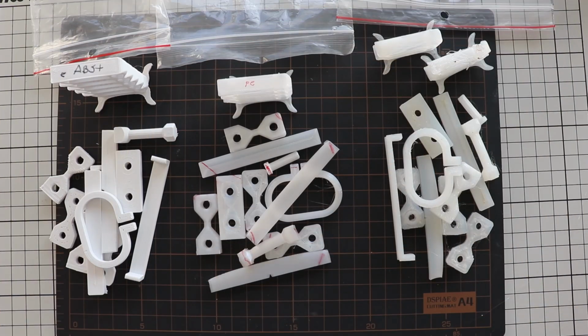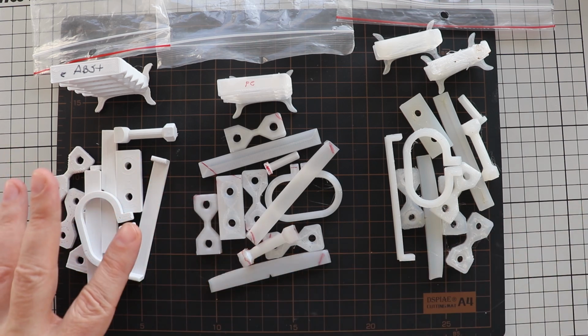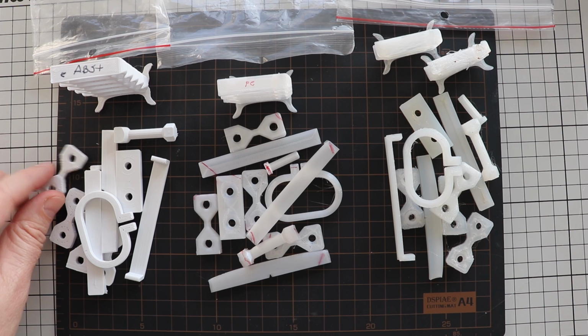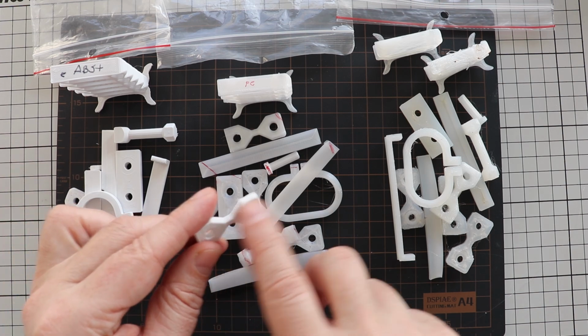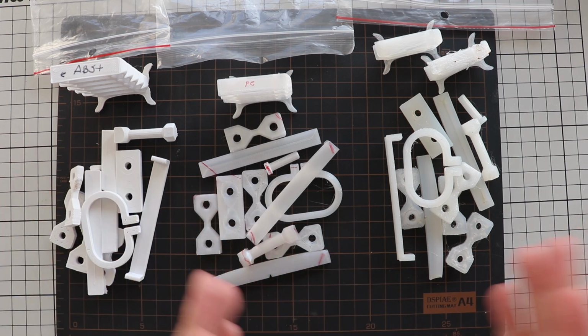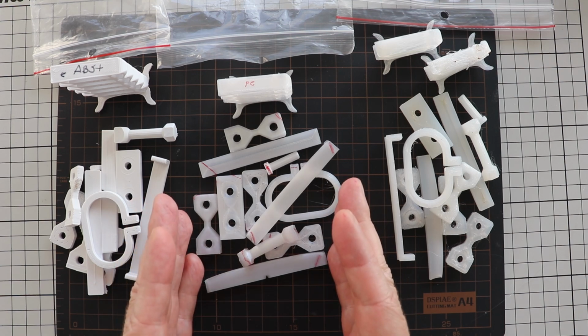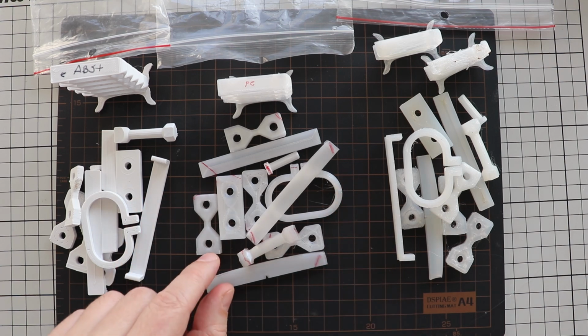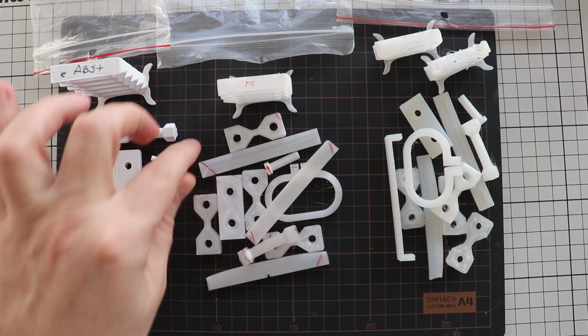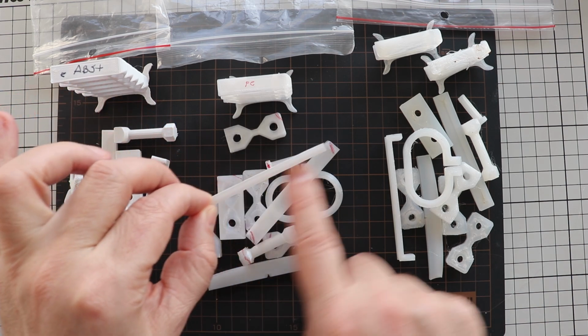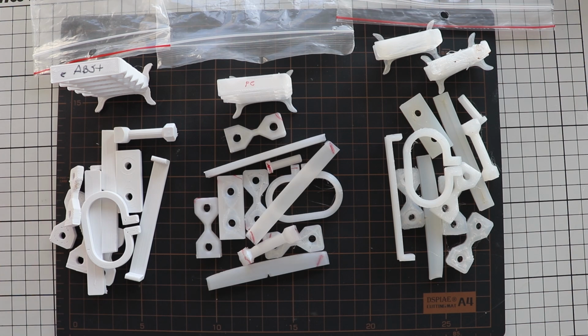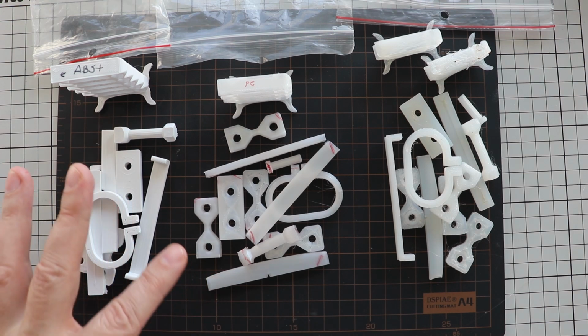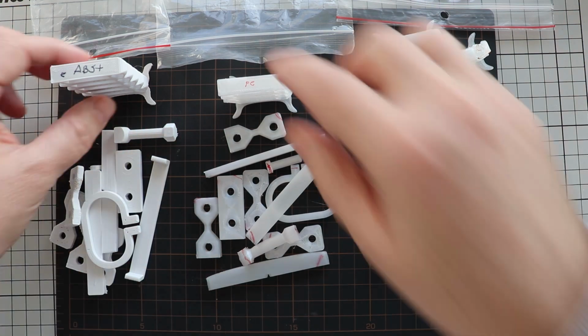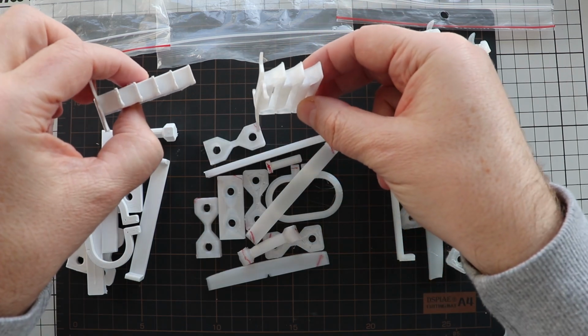There, all test specimens are printed now, and before I start with mechanical testing, first a quick overview of the printing. Actually, the easiest for the printing was the ABS. The only problem I had was with the overhang. The next one was the PC or polycarbonate. Here the only problem I had was the warping on some elements. For example, you saw this for the bending test, but everything else was quite good. Even better overhang compared to the ABS.